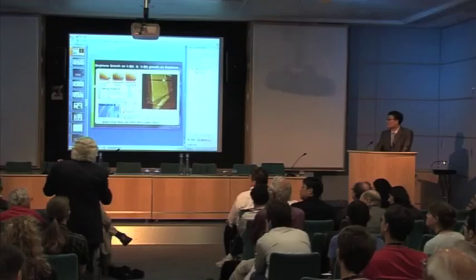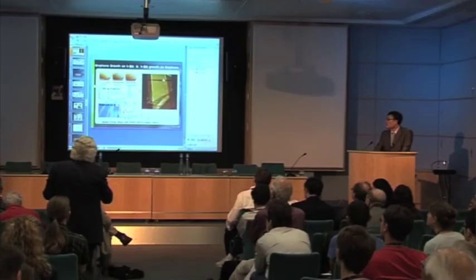It's very hard to explain. I was about to ask you a question, but maybe I can make a comment about that. About 2 years ago, a group at the University of North Texas sent us samples of this boron nitride graphene. And as I see from this picture, it has the same problem, a very large D peak. It just doesn't grow well. But any surface will give you graphene because that's a stable form of carbon, provided that you have enough thermal energy to decompose the gas. And people now report just about everything, certainly gold and other metals that do not interact. So the catalysis part is not very strong, you just need heat.